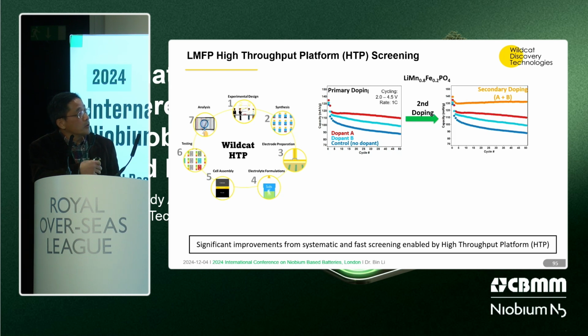And then we do, as I said, this is the first round. We do this one, we learn from this, and do the second round, those high throughput screening. So we combine those A and B dopings. Of course, A, B could be very different transition metals or main group metals, right? They have a different function. Now, then you see the synergetic effect when you have the doping A and B. And here, you see you get a much better cycle life. Initial capacity also improves a little bit.